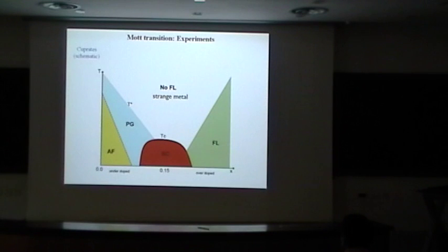There's another example of a different type of Mott transition, namely a Mott transition driven by doping. And I've just taken one very popular example, namely cuprates. So this is the cuprate phase diagram, which you have all seen many times, temperature and doping here. And the Mott insulator now resides on this axis, which is the half-filled limit. And then interesting physics happens upon doping of this Mott insulator, and among others, there is superconductivity. So I will come back to this actually in the third lecture where I discuss cuprates.